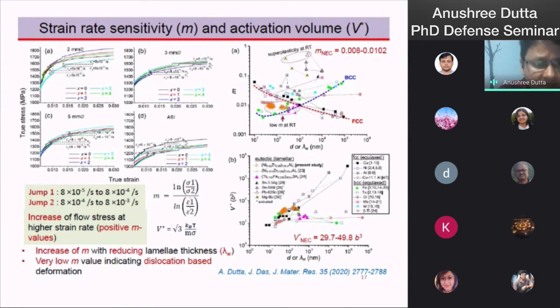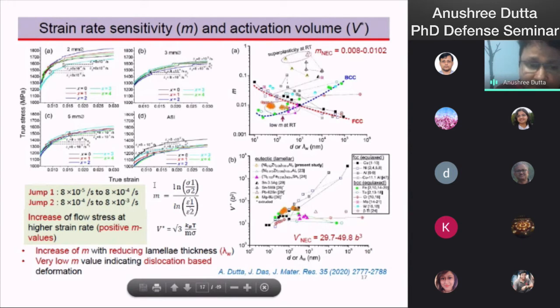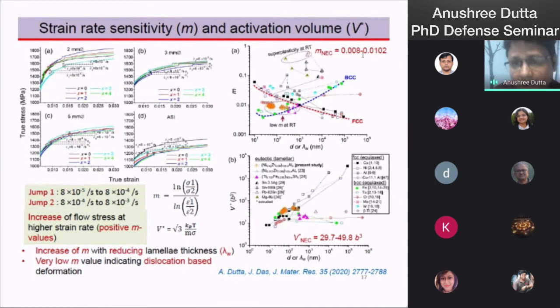In all the cases, we can find that the flow stress increases with increase of strain rate. That is positive. The alloy exhibits a positive strain rate sensitivity value. The strain rate sensitivity value has been calculated from this equation, and the activation volume has been calculated from this equation. The alloy exhibited a very low m value, which lies in the range of 0.008 to 0.0102, which indicates that a dislocation-mediated deformation mechanism is activated for these nanolamellar eutectic composites.